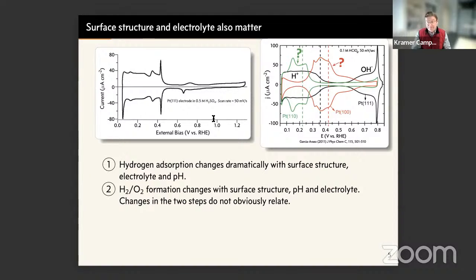Okay, so now you can do more experiments. I said, what about the interface? You can compare the voltammogram that you collect on a platinum 111 working electrode with voltammograms collected on different single crystals of platinum. On the left is the same plot I showed you before. On the right is a figure I've taken from Nuria Garcia-Araez and Juan Feliu from 2011. What they show here is this same voltammogram. Black is once again the 111, red is the 100, green is the 110. And what you will note is that this looks very different. Here is this hydrogen adsorption feature on the 111. On the 110, this current feature looks quite different. On the 100, it occurs at much more positive potentials.